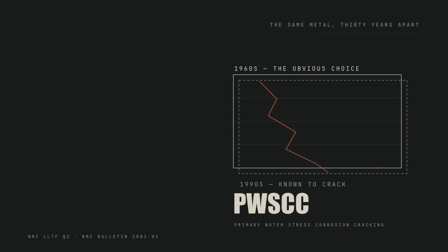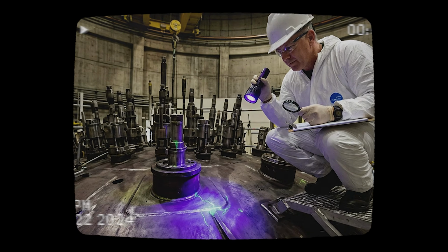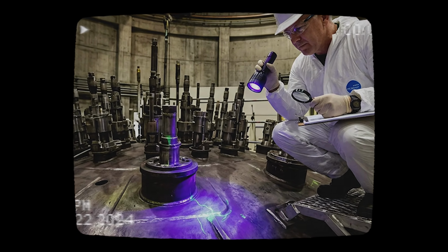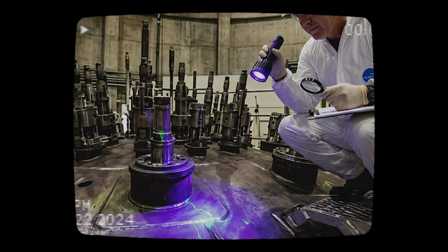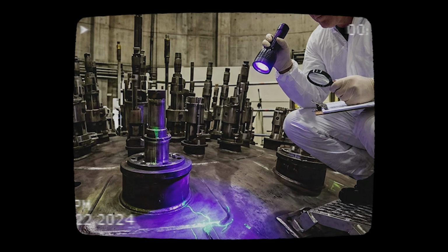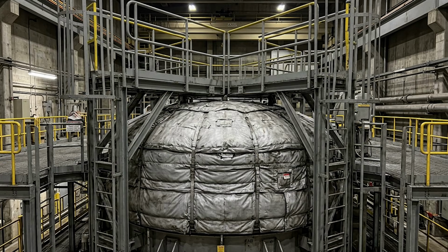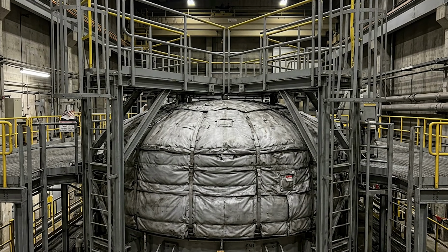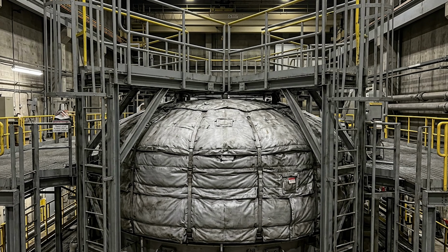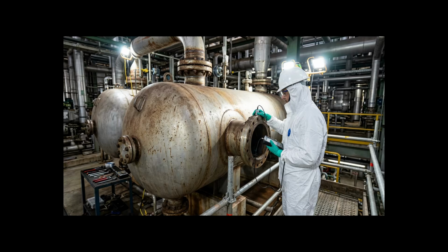By the 1990s, the industry knew something about it that mattered here. Under sustained stress, in hot borated water, alloy 600 cracks. The mechanism has a name: primary water stress corrosion cracking. And it is slow, and it is quiet, and it produces cracks you can only find by going up on that lid and looking. Which brings us to the second half of the geometry. You cannot easily go up on that lid and look. The head is covered by an insulation package and a service structure. To inspect a nozzle, you need access, you need time, and the plant needs to be shut down and cooled. Every hour a reactor spends shut down is an hour it is not selling electricity. Hold that thought. It comes back with a date on it.